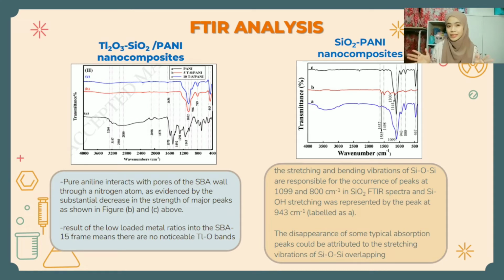Let's move on to the results and discussion. The first one is the FTIR analysis. For thallium trioxide silica polyaniline nanocomposite, the pure aniline interacts with the pore of the SBA wall through a nitrogen atom, as evident by the substantial decrease in the strength of the major peaks as shown in figures B and C above. The result of the low loaded metal ratio in the SBA-15 framework means there are no noticeable thallium oxide bands.